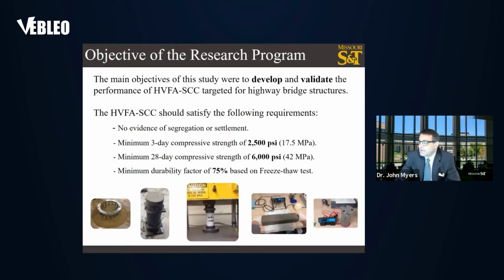As you can see here, the main objectives of the study were to develop and validate the performance of this new targeted concrete for highway bridge structures. In order to be successful, we have to work to develop a mix that has no evidence of segregation or settlement, that has a minimum 3-day compressive strength of 2,500 PSI, and a 28-day strength of 6,000 PSI.